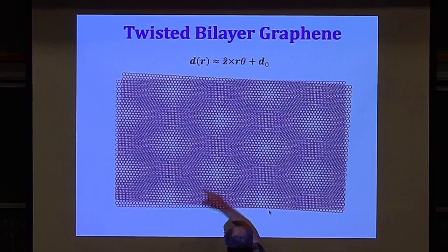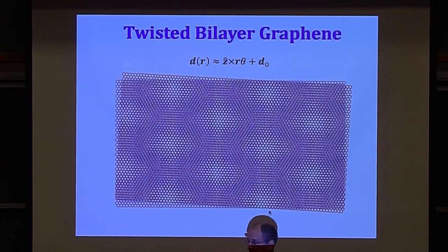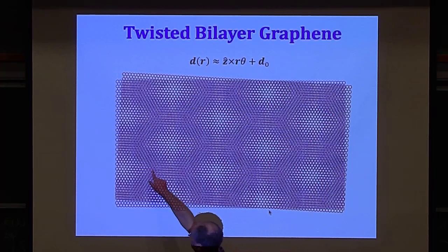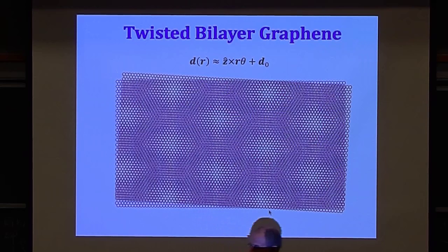Suppose I start by putting the atoms on top of each other with 0 angle. That's my reference configuration, and then I do the twist. I can do something else: I can start with respect to this configuration and then do the twist. Now, it turns out that for small angle, the behavior would be almost the same. It doesn't actually matter. If I have more than 2 layers, then it would matter a lot. It would change the properties completely. But there's something special here about 2 layers only.